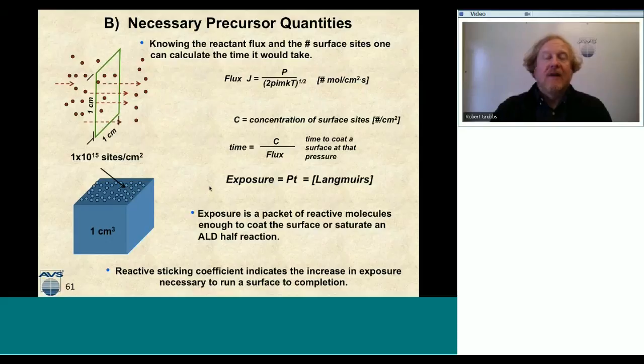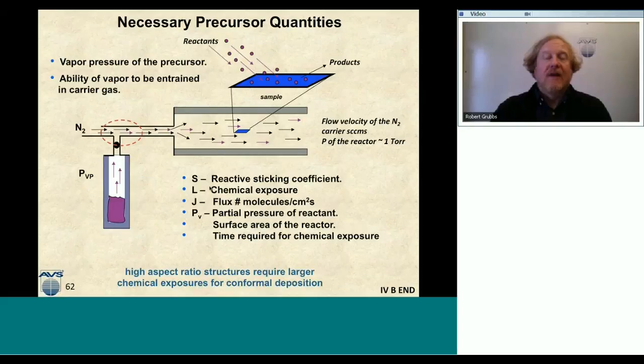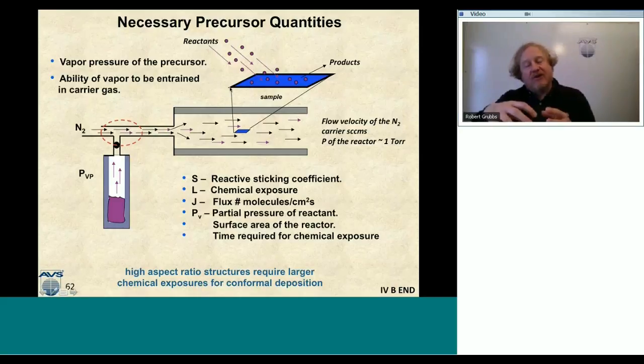So here's a cartoon of a reactor. I've got this liquid over here. I've got this nitrogen flow that's constantly flowing through my reactor, typically to keep the reactor at about a torr. Then I've got my surface right there. Reactants are coming down and products are being generated. So I need to know the reactive sticking coefficient of my process. Then I need to calculate the exact reactive chemical exposure I need in order to have that reaction run to completion. Then from there, I can calculate the flux of molecules that are actually hitting the surface.